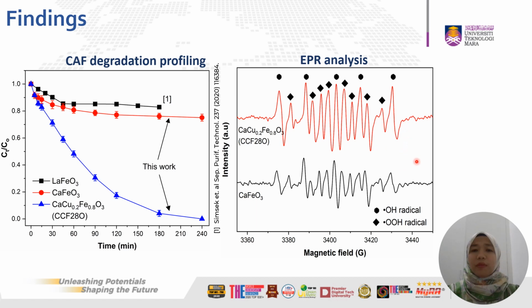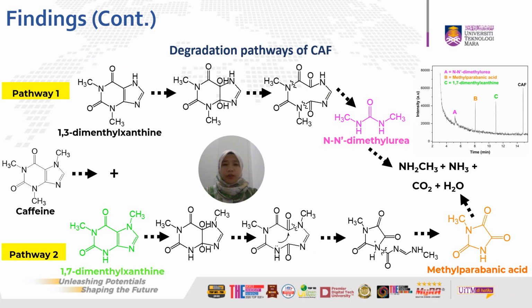Interestingly, as confirmed by the EPR analysis, CCF28O was effective in producing the hydroxyl radicals, which is responsible for the decomposition of caffeine. The identification of the caffeine's intermediate compounds during the reaction was determined using the GCMS analysis. Three main intermediates were found for the caffeine degradation, which are N,N-dimethyl urea, methylparabanic acid, and the last one is dimethyl xanthine.